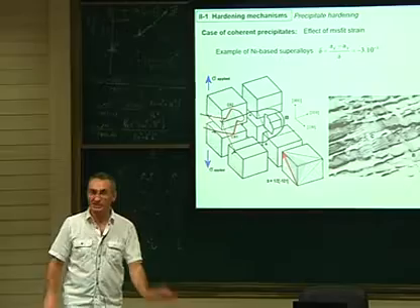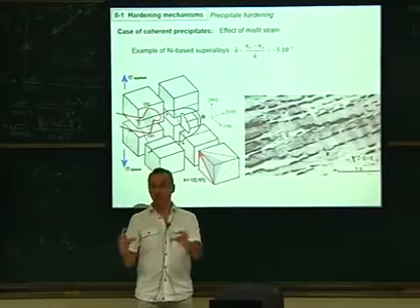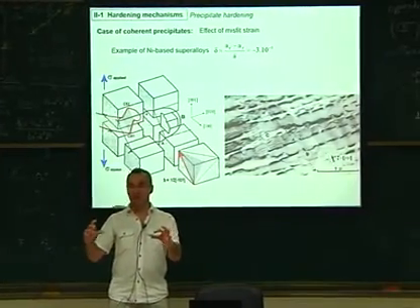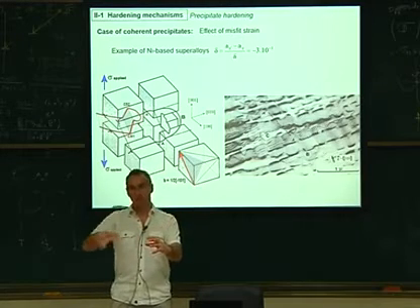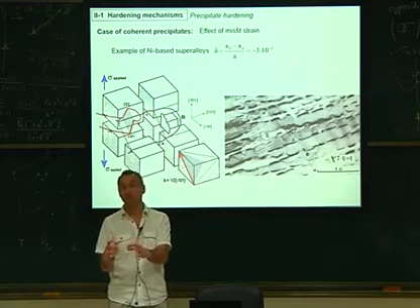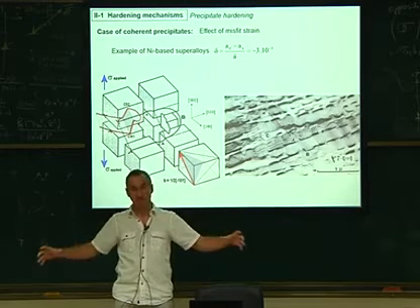Okay. No, precipitates are not moving. So precipitates were just randomly put in the box. Initially they were totally separated, but as soon as you have put 3 or 4 loops, then the internal stress is merging, just the stress field. The loops are not even touching each other, but the stress field is merging because it has a long range effect.